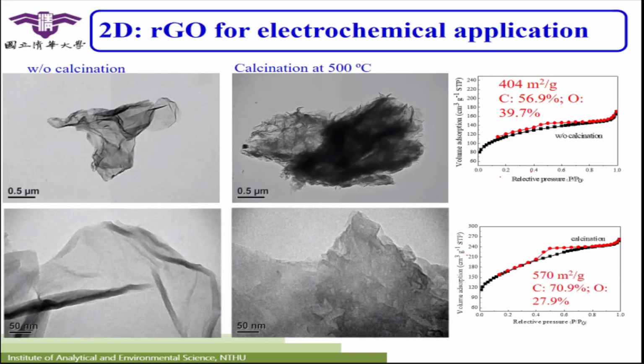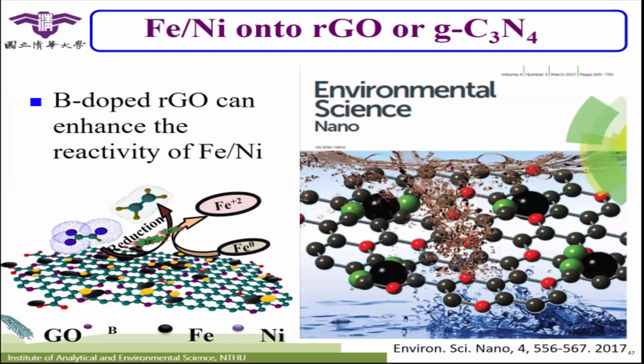This one is the case for graphene and reduced graphene oxide, so we can see the sheet here. The surface area is around 404 to 570, which is relatively high. We immobilize some metals on the surface of reduced graphene oxide, and you can see that they adsorb very good. So when we use this one,